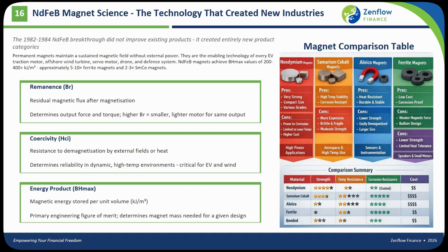Without NdFeB, the modern EV traction motor, the compact hard disk drive, the wind turbine generator as we know it would not exist. Permanent magnets maintain a sustained magnetic field without any external power input. NdFeB magnets achieve the headline performance metric, an energy product of 200 to 400 or more kilojoules per cubic meter, approximately 5 to 10 times better than ferrite magnets, which are the cheap, common alternative, and 2 to 3 times better than samarium cobalt